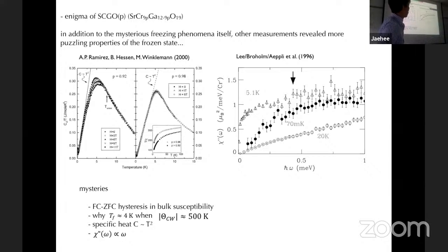So just to understand it again. For an ordinary spin glass, the energy dependence of the susceptibility would just flatten out and stay there at low temperatures. That's right. And what you see here is that it goes down again, which means that you don't have excitations at these small energies. It's like a well-defined spin wave excitation. And a question about these susceptibility measurements, these temperature measurements: do they depend on the cooling rates? Oh, that's what I'm going to tell you. Oh, memory effect. Very good.